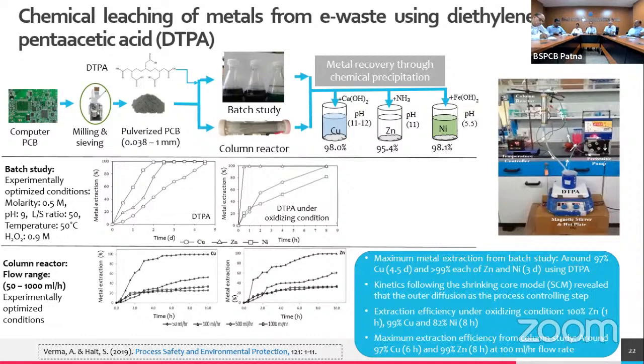Once the metals are extracted, we need to recover them, because they are present in solid form. By doing this chemical leaching using this organic acid, we bring them into the liquid medium. Once they are in the liquid medium, we need to recover them, in terms of, let us say, metal oxides. There are several procedures. One procedure is selective chemical precipitation. As you can see, the extraction efficiency was 97% for copper and greater than 99% for zinc and nickel. Further, we recovered 98% of copper, 95% of zinc, and 98% of nickel from the extracted medium.